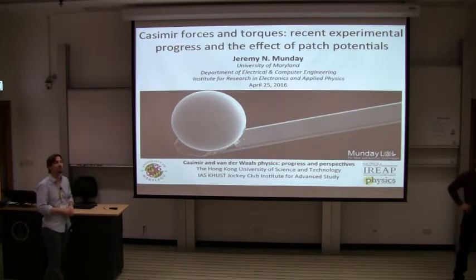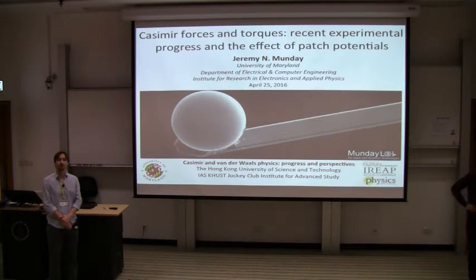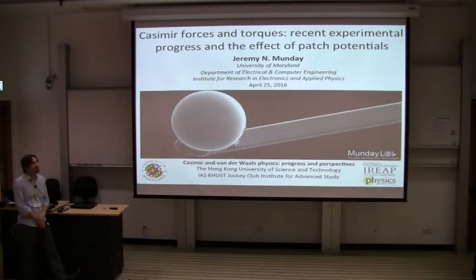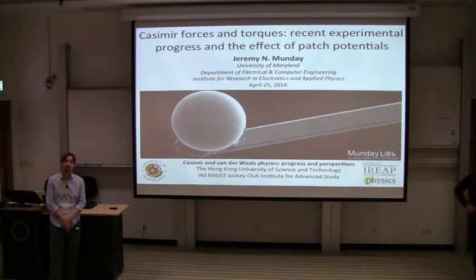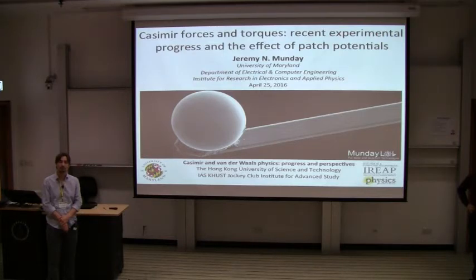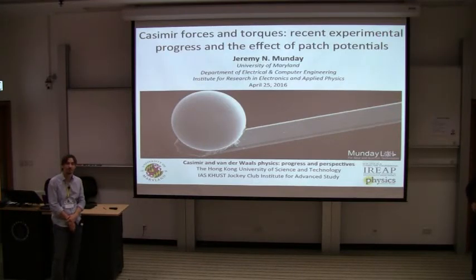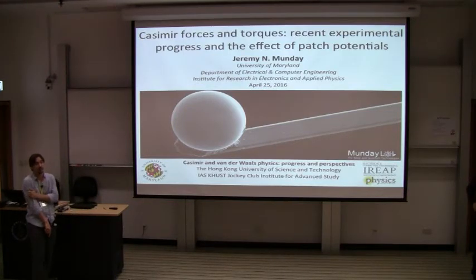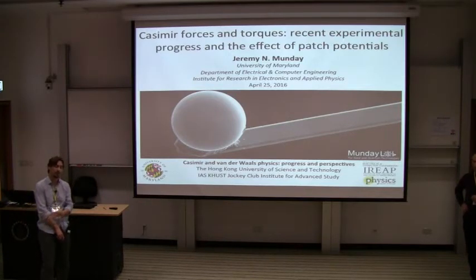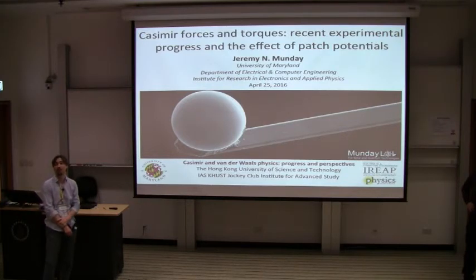Is the effect of humidity reversible? So if you change it back, does the result go back to the previous ones? And second, when you do the Kelvin probe microscopy, then do a Casimir measurement, and then do Kelvin probe microscopy again, are the results reproduced, or do they change as a result of having another surface in contact with this one? Yeah, a few parts to this. With bringing the humidity down and then bringing it back up, we do see some variations; they don't come back to quite the same value. So we're still trying to figure out why that is. What we're working on now is trying to characterize both surfaces and then make Casimir force measurements to see how that varies. I think that's a good question. We're also trying to understand whether it varies with time. If we just look at these samples, we think our system is stable, but do the patches vary with time? Those are still open questions.